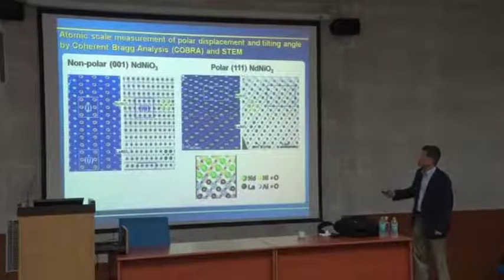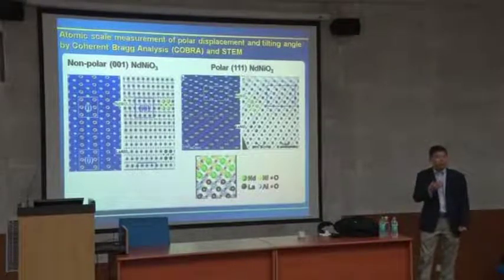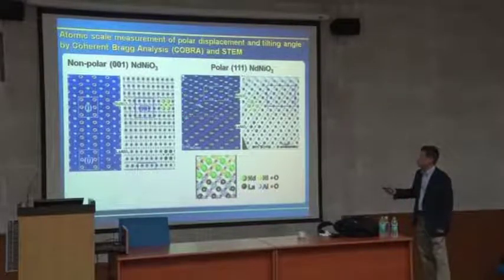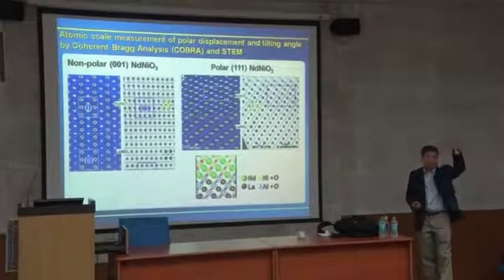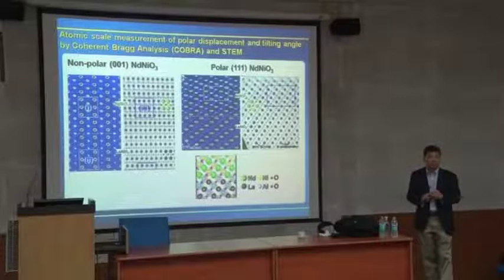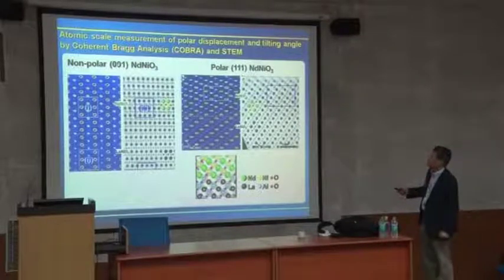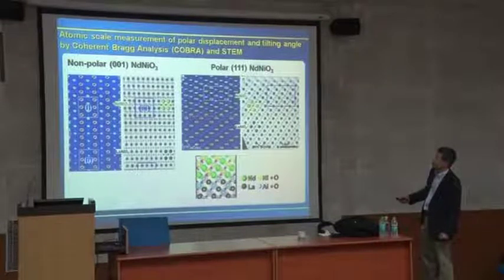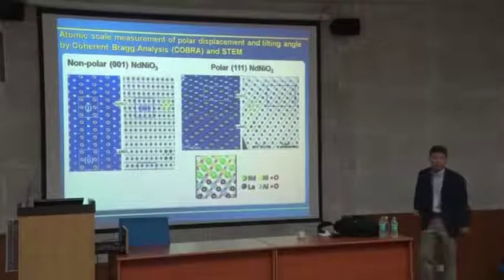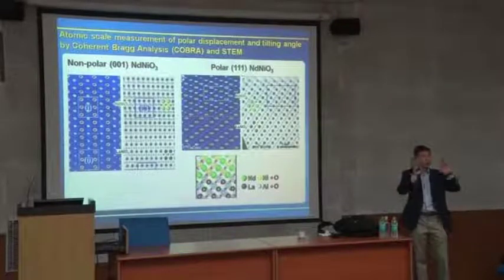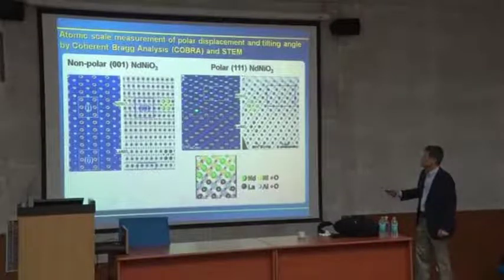And then this is another method, synchrotron, what we call coherent Bragg rod analysis measurement, which is imaging of all the atomic positions using synchrotron X-ray surface diffraction. So these two are showing 001 and 111. You have two different ones, maybe hard to see what the difference is. And this is the synchrotron X-ray diffraction showing all the electron density map. So your synchrotron diffraction can tell where your electron density is higher, and then you get brighter. Electron density lower, you get the lower. So you have all these atomic positions.